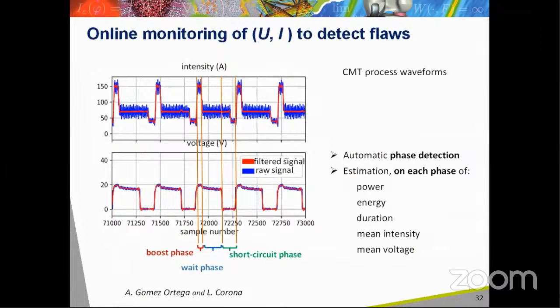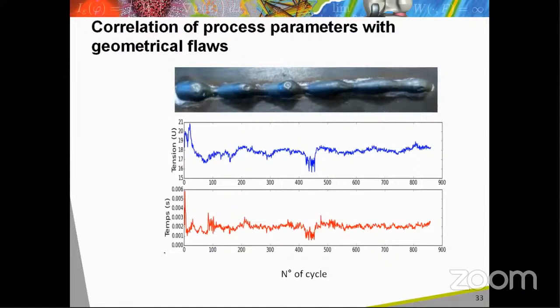In order to try to detect geometrical flaws from the electrical recording, the three phases of the CMT cycle, the boost, the wait, and the short circuit phases, are automatically detected, and some parameters of each phase are computed, such as the power, energy, duration, mean intensity, and mean voltage for each phase of each cycle. These results were compared to the geometry of numerous deposits obtained with various process parameters. This work has shown that some of the computed parameters are good indicators of the geometrical defect.